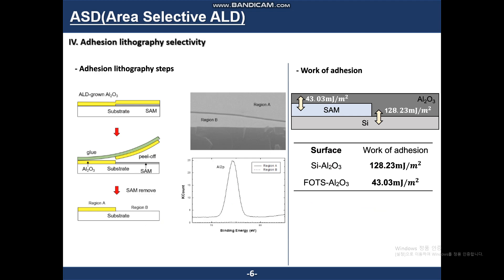After this deactivation work, I used an adhesion lithography method instead. This method uses the adhesion difference between several material surfaces. To apply this, I calculated the work of adhesion between materials. By this, I found that the adhesion between alumina and the silicon substrate is higher, so by using adhesion lithography, I can pattern on the surface and lift up patterned alumina.